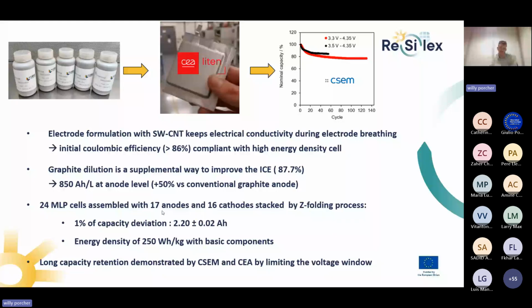And so 24 multi-layer pouch cells were assembled with 17 anodes and 16 cathodes, stacked by Z-folding process. We had 1% of capacity deviation on the cells assembled, and we demonstrate an energy density of 250 watt-hour per kg with basic components. And finally, we demonstrate a long capacity retention by two partners by limiting the voltage window.